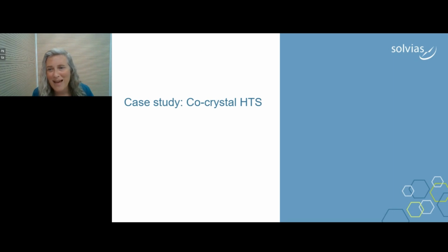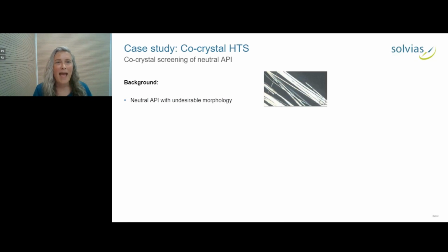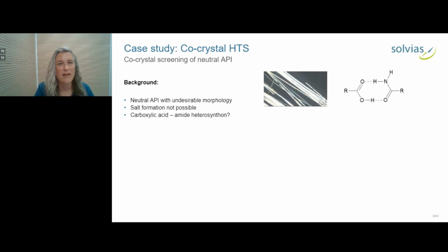So with the remaining time here, I would like to just go through two case studies. And the first is a co-crystal high-throughput screening. And in this case, we had a neutral API with an undesirable morphology, very long needles, a high aspect ratio, and we screened various solvents, but there was no way to crystallize this directly in any other morphology. And so because it's neutral, there were no acidic or basic sites, we couldn't form a salt.